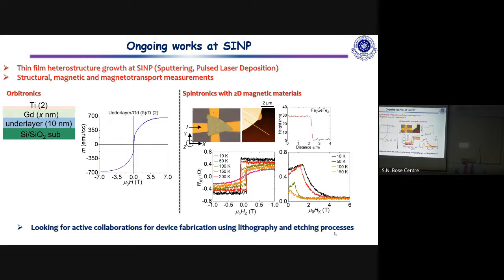The domain size doesn't depend on the lateral dimension, only on the thickness. That was what was shown when they made these really thin flakes. But it should also depend on the lateral size. I think the dipole interaction is changing when you are reducing thickness, and then it becomes single domain. Even if you isolate one monolayer, I don't think it would be single domain. There should be a critical size. There is a critical size, but roughly of these dimensions, which is around 5 microns. Most of the experiments were done on this kind of sample.